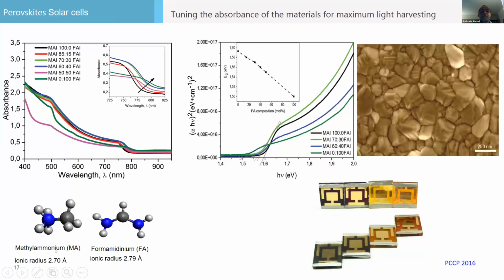Similarly, we were working on methyl ammonium, then we shifted to formamidinium, because formamidinium has one NH2 group extra, and the ionic radius is a little bit higher. So you can change the composition, and by changing the composition, very systematically, you change the band gap of the material. And also formamidinium, you can see, has a higher band offset here. So this was a very old study. We did a 60-40 ratio, formamidinium 40%, methyl ammonium 60%. You can see the crystals here.